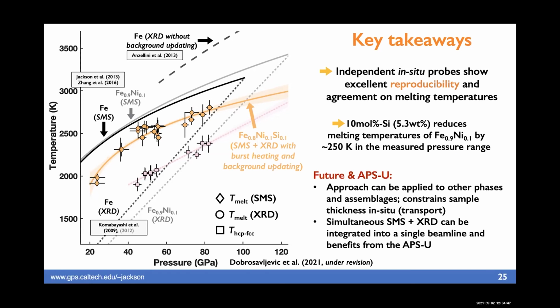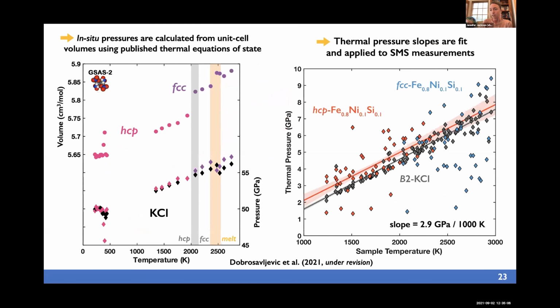Yes, good. Nice talk. Can you explain how you determined thermal pressure from your XRD data? Yes. So what we did was we measured the unit cell volumes of the sample and of KCl. The sample's equation of state was determined in the Morrison et al. paper, along with the thermal properties. We use that equation of state to determine the pressure of the sample. We use the equation of state of KCl to determine the pressure at the pressure medium. What you see on the right is the very good agreement between those pressures. And we take the average of those two pressures, and those are the pressures that we report for the melting points.